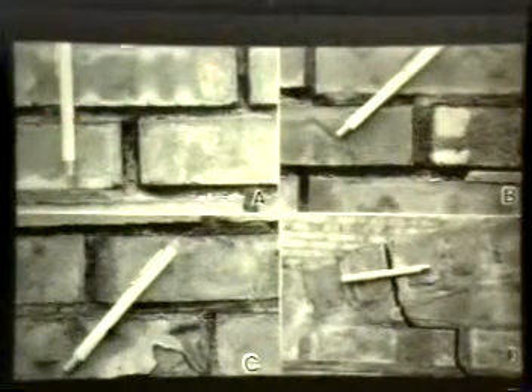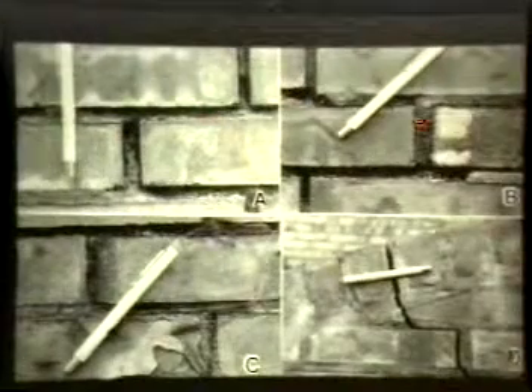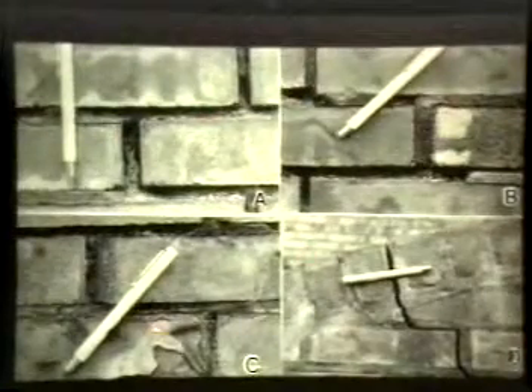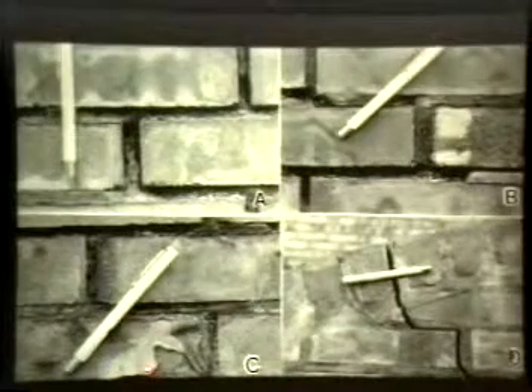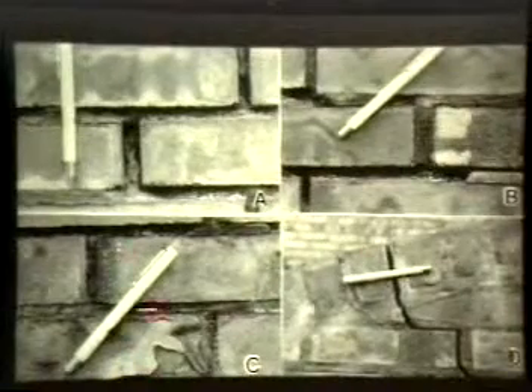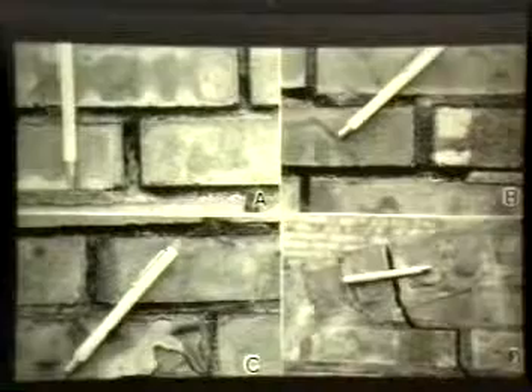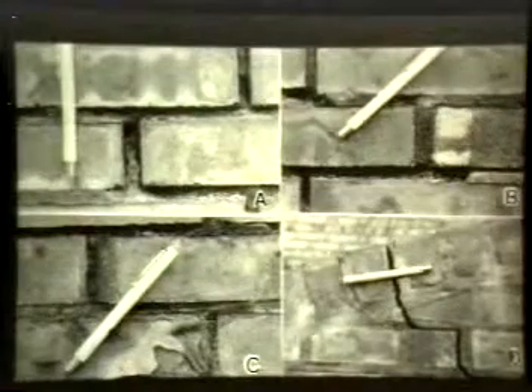Next, please. This is a brick mortar structure. As you can see, efflorescence affecting the bricks and the mortar. Next, please. Some more examples. Here you can see efflorescence beginning. You can see the mortar eaten away. Here again you see some of those. You can see some scaling of the brick, and after the mortar has gone away, you can see the cracks. Mortar has been completely disintegrated.